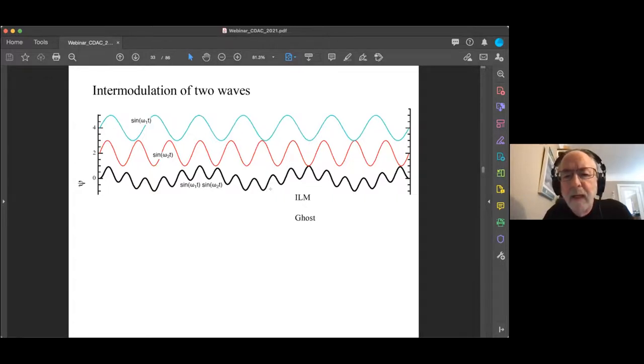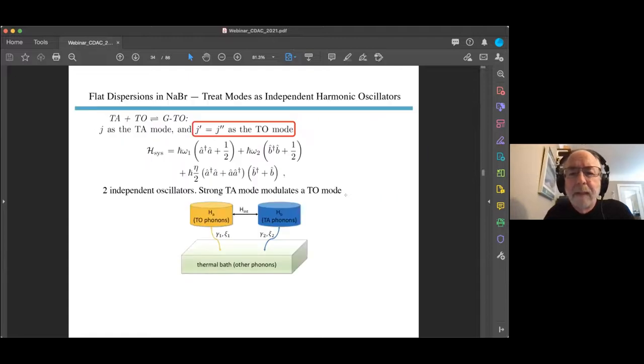We can make these in terms of a sum of the two frequencies, and the differences would give these high frequency oscillations in this long wavelength. The long one is the intrinsic localized mode, and our ghost mode is this high frequency behavior here. Sorry, there's an animation there. Turns out that the laser physics community has been doing a lot of work with this, with laser cavity experiments, where they get sidebands around their laser frequency when they detune slightly from the cavity resonance. They've done an elaborate analysis for photons, which applies very well to phonons.